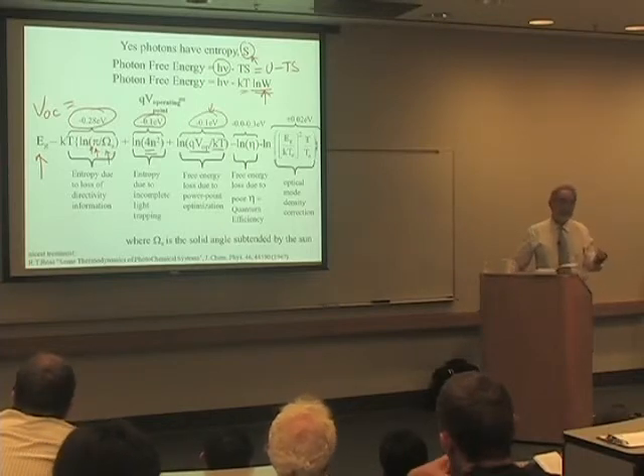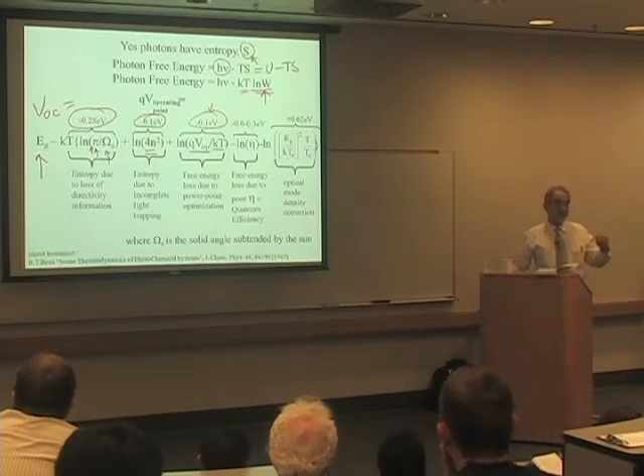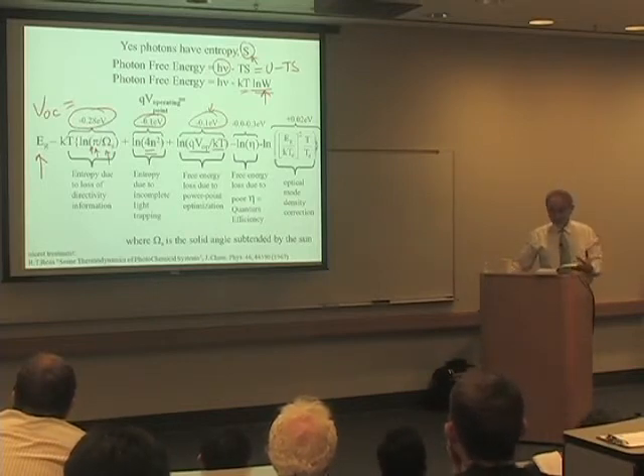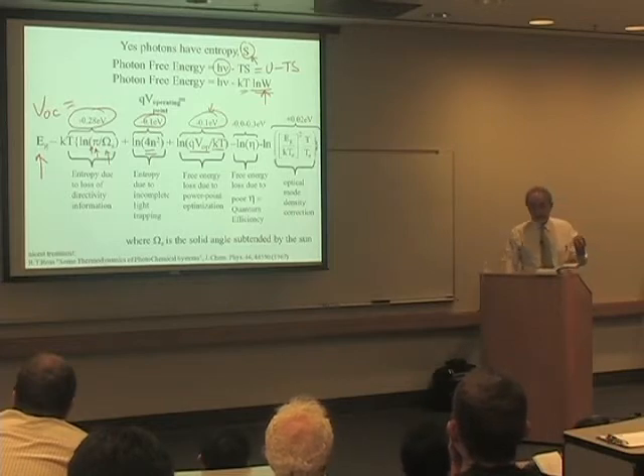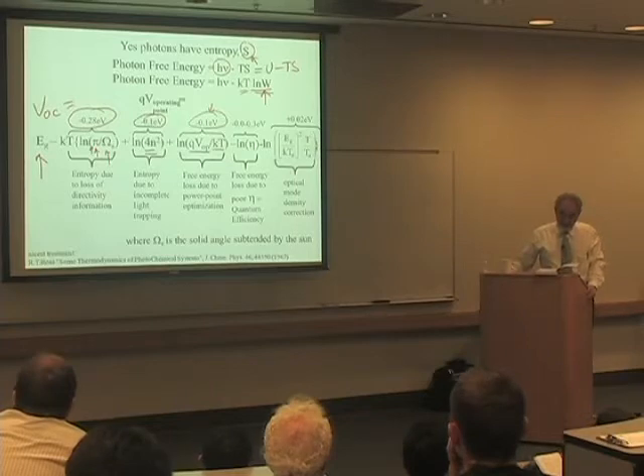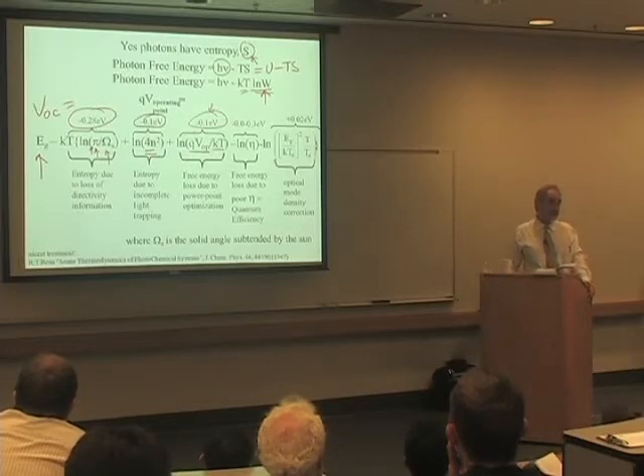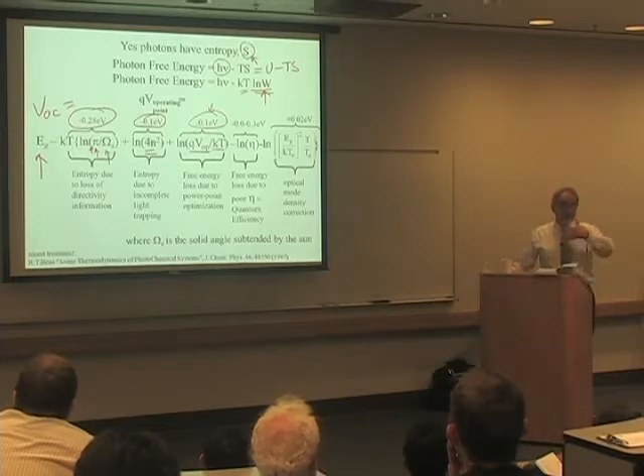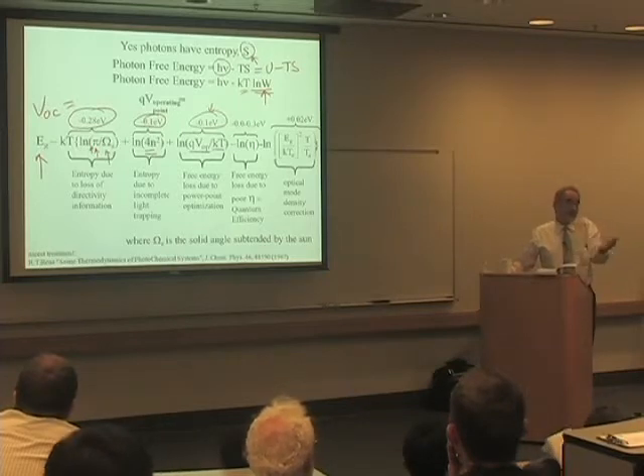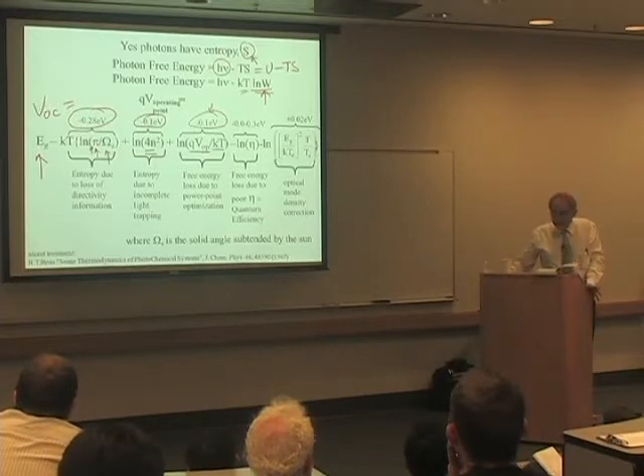So the ideal situation, the best semiconductor, would be a material that luminesces well. This was actually pointed out by Shockley, and this was the basis of the Shockley theory for the open circuit voltage. What he said is if you have a solar cell with no non-radiative recombination, that means that at open circuit, every photon will come back at you as luminescence because it has no place to go. There's no non-radiative recombination. So that's the ideal situation, 100% luminescence efficiency.